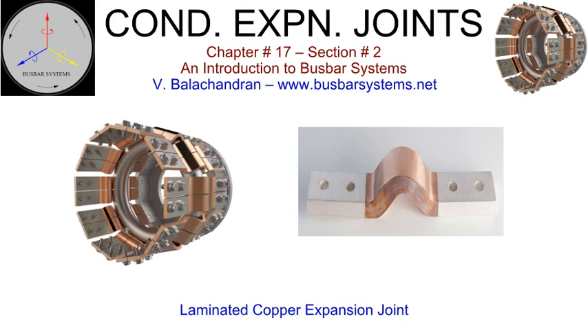This process requires extreme care to prevent any ingress of electrolyte between the shims during the plating process. It may not be possible to wash the electrolyte thoroughly and the same may surface later, resulting in corrosion and green salt formation. Copper laminated flexibles can compensate only in two directions. They cannot compensate for the movement in the lateral direction. Twisting the ends of the laminates during installation should be strictly avoided.